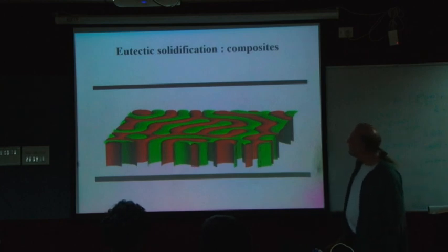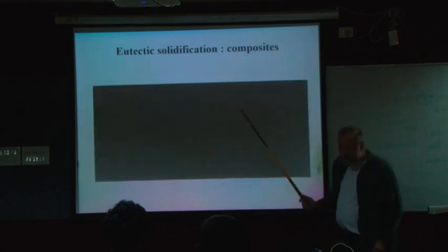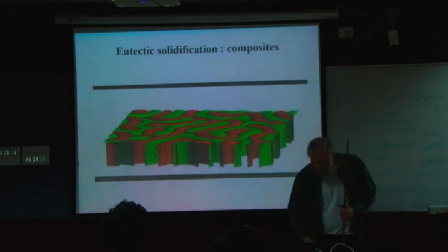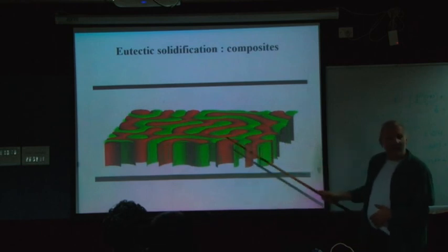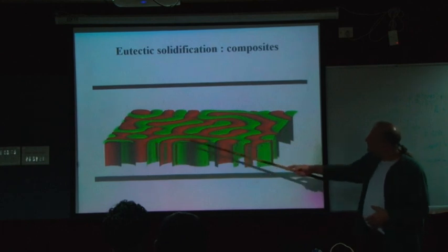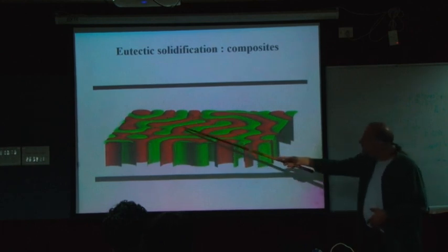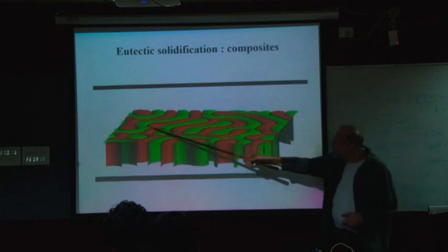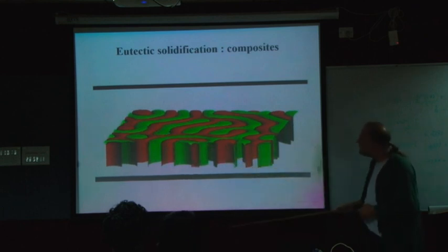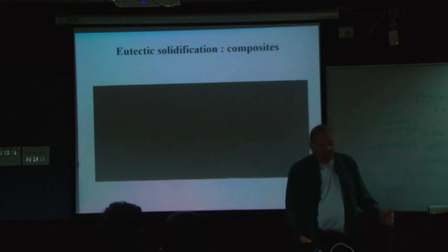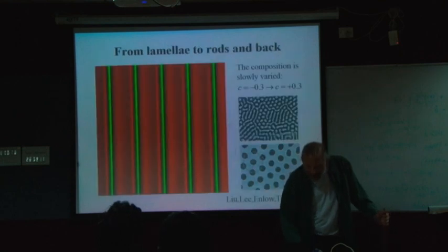Ooh, the resolution is not very good here. Well, I think what you can distinguish is that rapidly you have a lamellar pattern, but it is not very regular. It has a sort of labyrinth structure. Here you can see a bunch of parallel lamella, and the simulation shows you how slowly the pattern orders. For example, here you have a reconnection event, and somewhere something else should happen. In any case, the total solidification length is about 20 times the lateral dimension of the sample. So you can do things on scales that are really interesting for metallurgical applications.